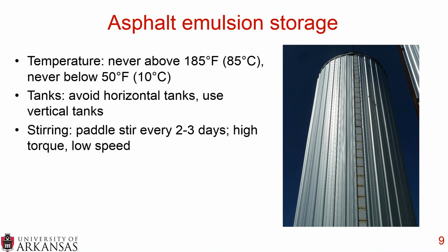You want to avoid horizontal tanks. You want to use a vertical tank like the image on the right, and that's just because of the surface area. Sometimes a skin forms on the asphalt emulsion, and that's just because the water is evaporating at the top of the tank, and so you have a smaller surface area with horizontal tanks, a smaller surface area of exposed asphalt emulsion. It's generally good practice to have paddles in these tanks, and you want to give it a very gentle stir every 2 to 3 days.